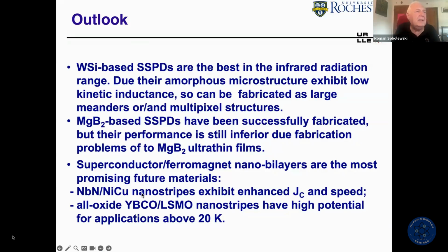Finally, there is a future in niobium nitride and nickel copper bilayers, which would have enhanced critical current and speed. And there are reports on YBCO detectors, but again, YBCO in a bilayer with a magnetic perovskite seems to give better performance. But the reason is that you really don't want to go to very high temperatures because then you start to have very high thermal noise. So being at low temperatures is important. And YBCO has extremely short coherence lengths, so the size of the hotspot is extremely small. All this makes these devices very difficult to fabricate, especially if you would like to have commercial devices.